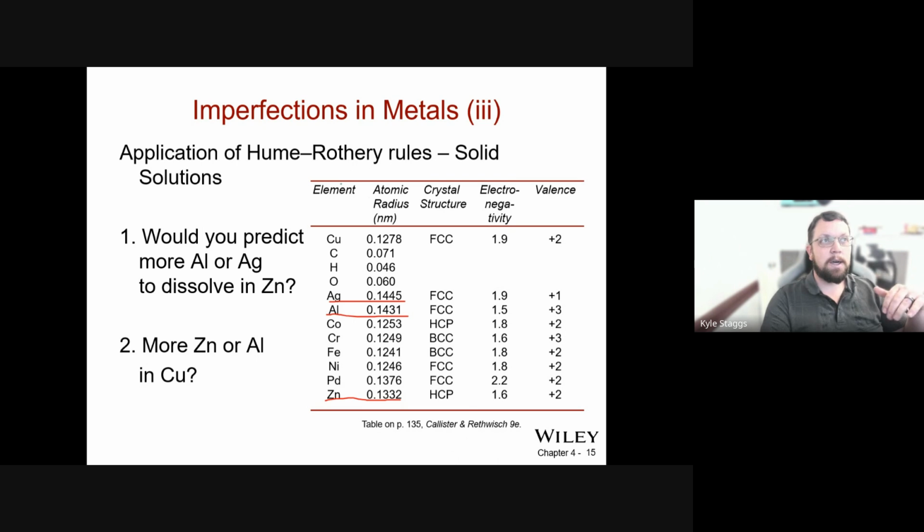So something like iron and chromium to make stainless steel makes sense. Iron being 2 valence and chromium being a 3 valence, and their atomic radii are very close, right? So it's very important to understand those aspects. Another one is, and we'll clear these.